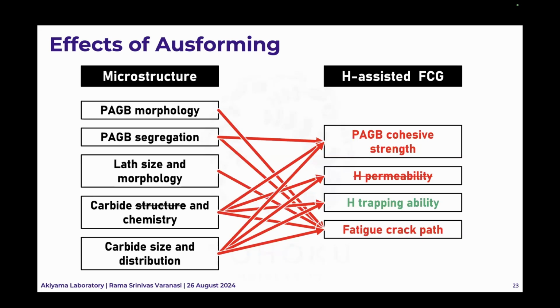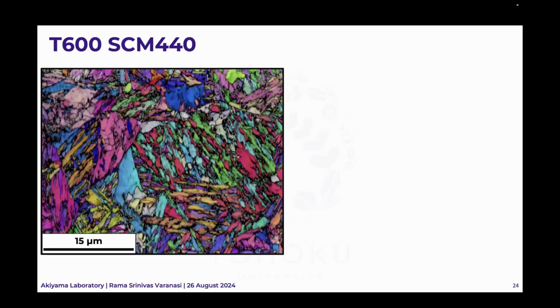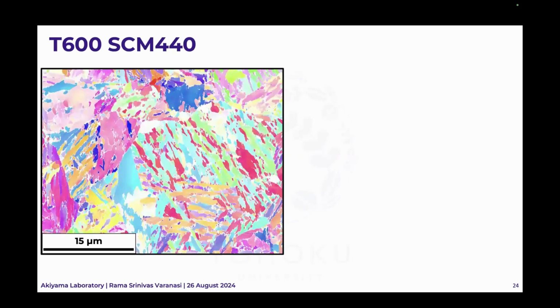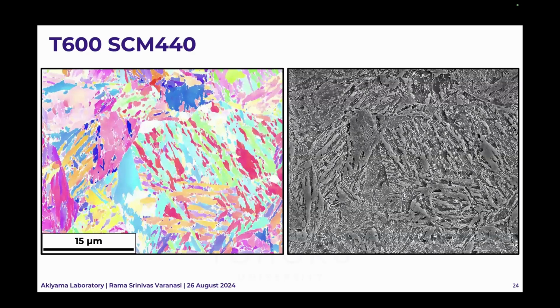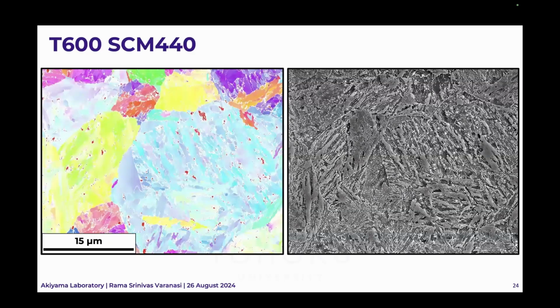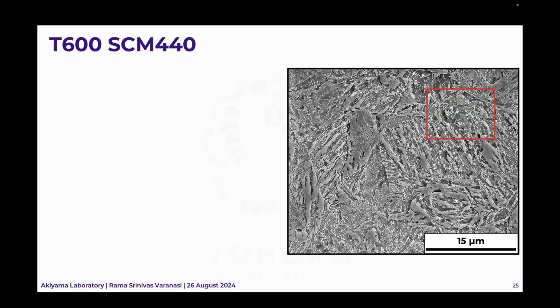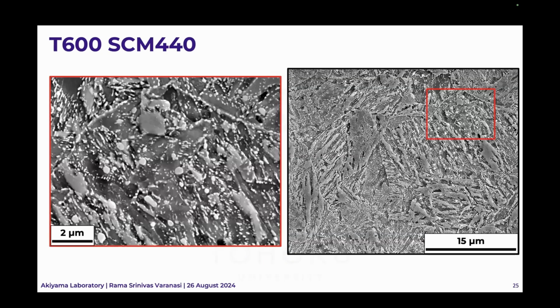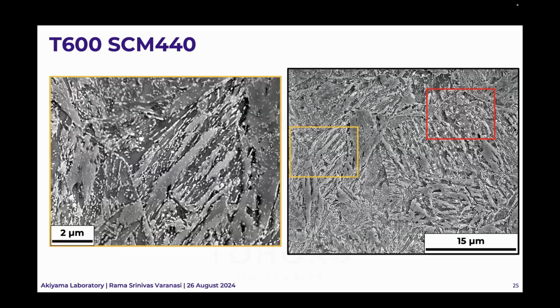But now we want to go back and see how the microstructure is affecting this. So this is IQ plus IPF, and this is the corresponding SE image. And we reconstructed the prior austenite grain boundaries in OIM. We can clearly see these prior austenite grain boundaries also in the SE image. And when we look closer, what we observe is the coverage of carbides on the prior austenite grain boundary is nearly 100%. We can look at a different area as well, and we will realize the same thing, that we have nice coverage of these carbides on the prior austenite grain boundaries.